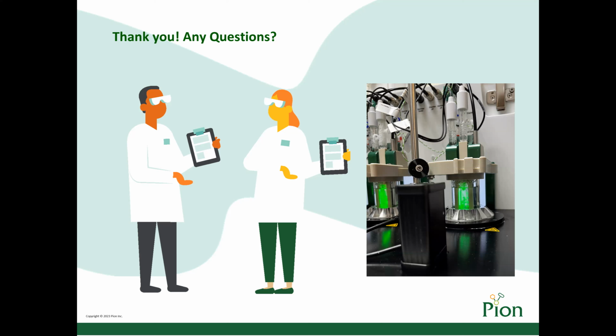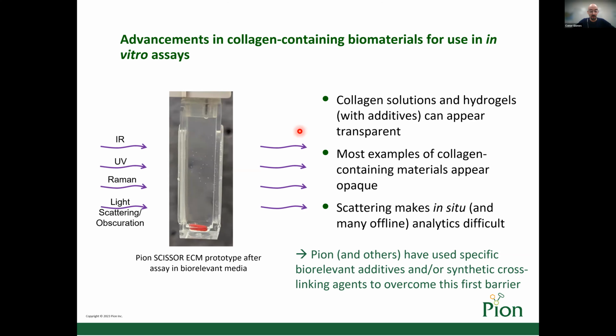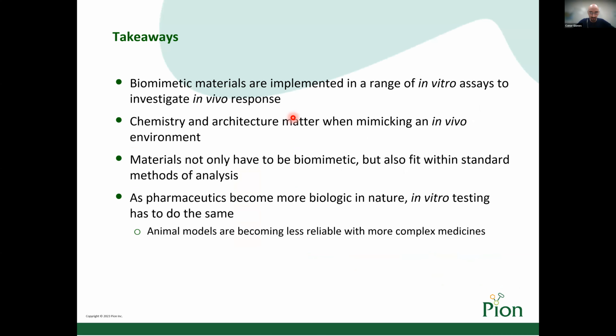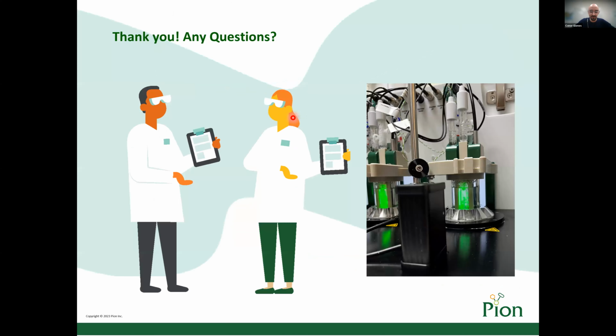Phenomena during injection, like aggregation and diffusion, can be seen through this cartridge with cameras and LED optical sensors, opacity sensors. You can see the LEDs lighting up the cartridge green in this image. As it leaves that green cartridge, Pion has a fiber optic spectroscopic tool called the Rainbow, where we can measure how much drug is coming out of the artificial ECM over time. That is what we would correlate to the in vivo response when it comes to drug release and mechanisms that happen after injection that would impede release as well.